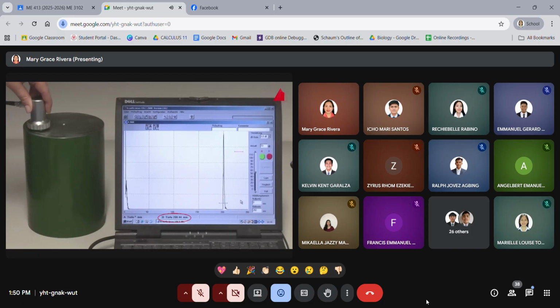The cylinder back wall lies in a depth of about 200 millimeters below the probe, so the cylinder has a height of 200 millimeters. And here we go. The material tester scans the upper front end of the cylinder with a probe and observes the monitor. A defect echo appears on the monitor. This defect is located in a depth of 130 millimeters below the surface.